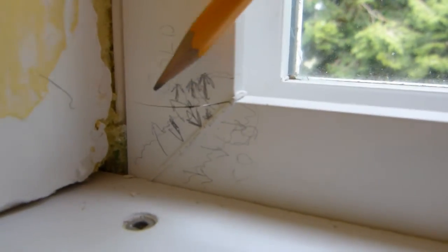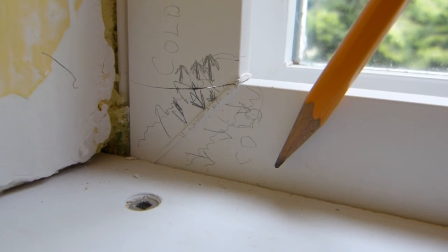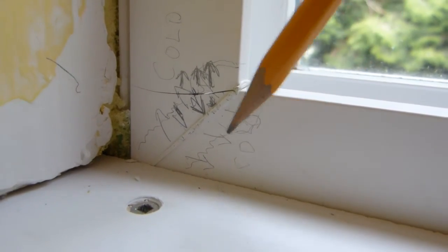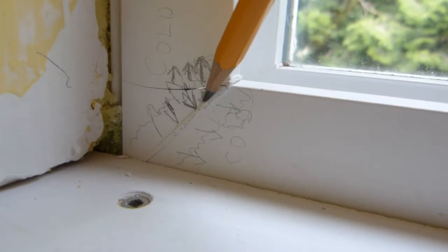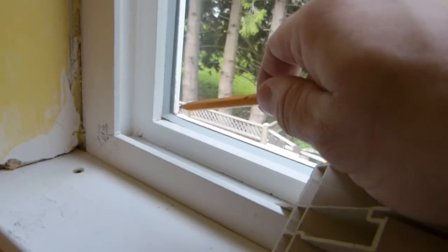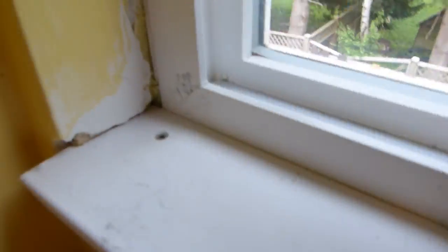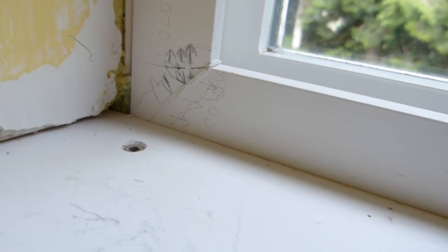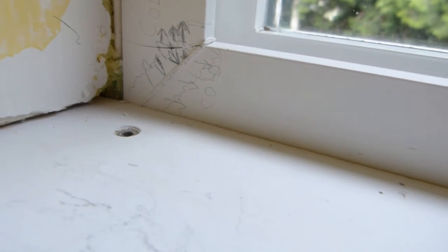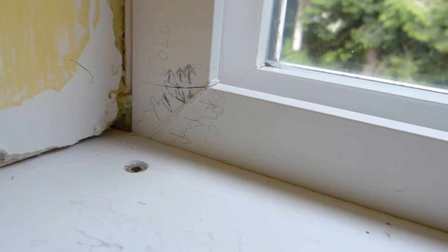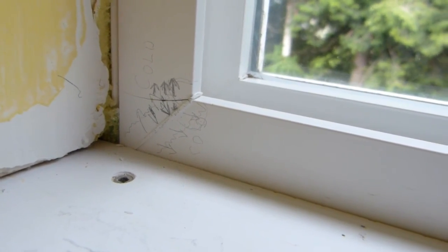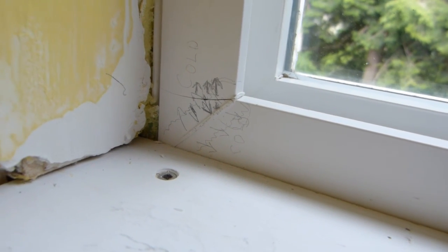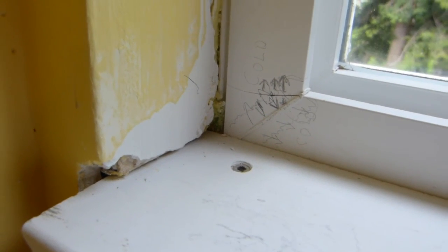So why did this corner fail only and not any other corners? That means that the piece was handled properly. For proper manufacturing, this piece has to be preheated, and cooled down in a controlled environment to avoid thermal shock to the joint there. Probably there was a sudden draft that hit only this corner and only this surface here, because there are no cracks on the opposite corner, no cracks anywhere else on the window. So it was a sudden blast of air, some kind of draft that hit only this corner at the manufacturer's site when the rig that's applied around plastic molding was opened for a second or so. So it's a manufacturing problem, and it's really hard to control.